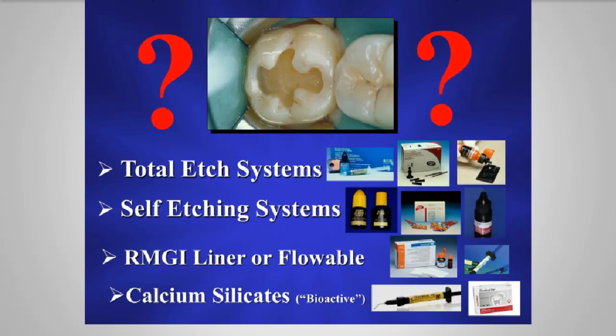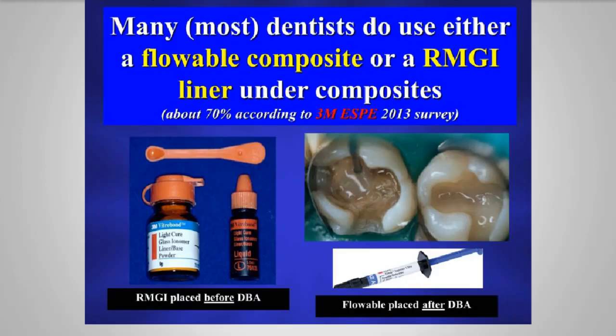In fact, according to a fairly recent 3M survey, about 70%, or almost 3/4 of dentists, are using one or another. The difference between them, by the way, is that the resin-modified glass ionomer liner should be placed prior to placing the dentin bonding agent, while a flowable composite should be placed after the dentin bonding agent is placed. Why use a flowable or resin-modified glass ionomer liner?